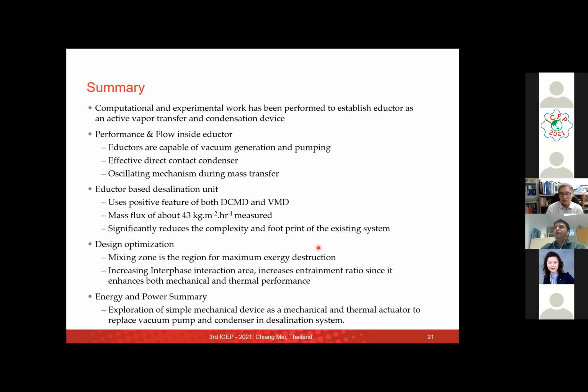So summarizing this result, when we study the performance, we could see that eductors are capable of generating the vacuum as well as functioning as an isolated condenser unit for water desalination systems, and we could achieve a result of up to 43 kg per meter square per hour. And there is some potential to enhance this mass flux by increasing the mass transfer rate, by increasing the interface interaction area, by increasing the number of nozzles in the eductor.